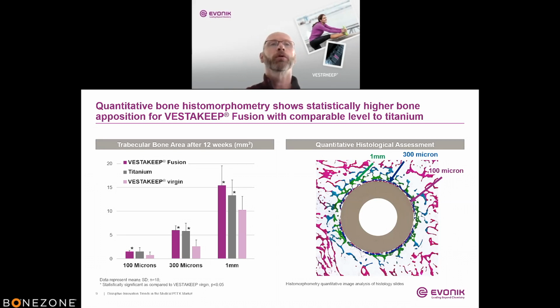At 100 micron and 300 micron at the end of 3 months, we're seeing a statistically significant difference between Fusion and virgin unfilled PEEK, and really consistent with what we see in titanium. Titanium obviously has a good reputation of on-growth, but it is a reactive material, and given a choice, some people prefer not to incorporate a metal implant into the human body.